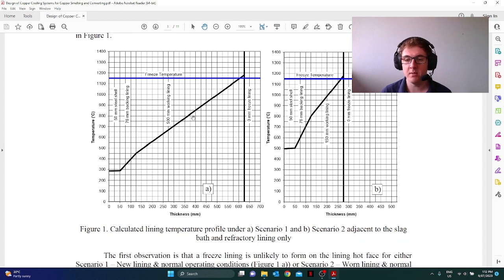In this one, you can see at the start of the campaign you have a hot steel shell at about 300 degrees Celsius. As you eat up the brick, your thermal gradients change and your steel shell temperature increases. The general rule of thumb I've heard for steel shell is you want to keep it below 300, 350 degrees Celsius. If you start to creep up, the steel shell starts to glow and it starts to deform. So glowing is the general rule of thumb; you go out there and you start to worry if it starts to glow. You can do things there.